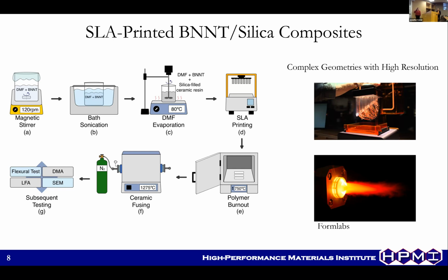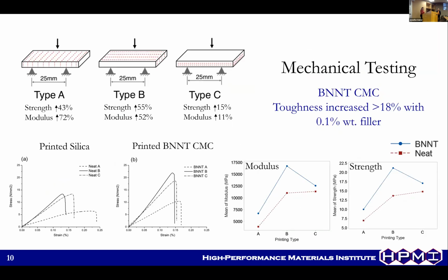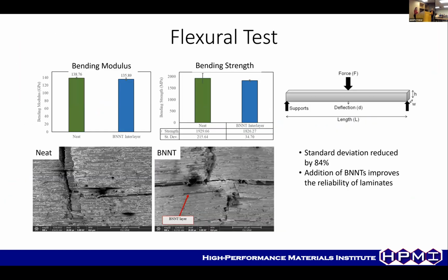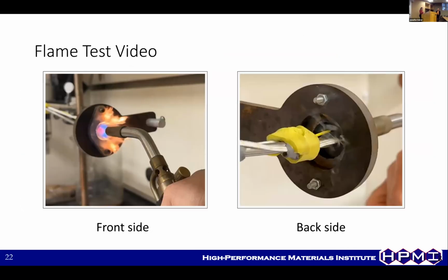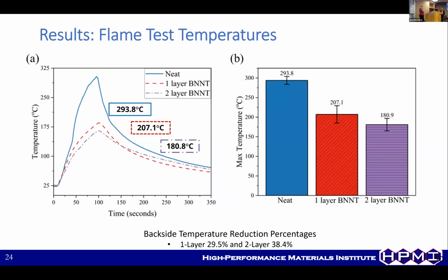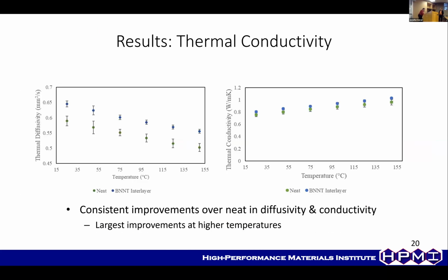Okay, so these experiments, the ablation, the flame test ones, have already been performed with CNTs. I would say they get similar performance, but the intrinsic properties of CNTs have lower oxidation resistance, so ideally they would perform worse. As far as the pressurized ones, they're about the same, but CNTs don't see this 40% reduction in backside temperature, which is likely due to their lower oxidation resistance, so it's less reduction.